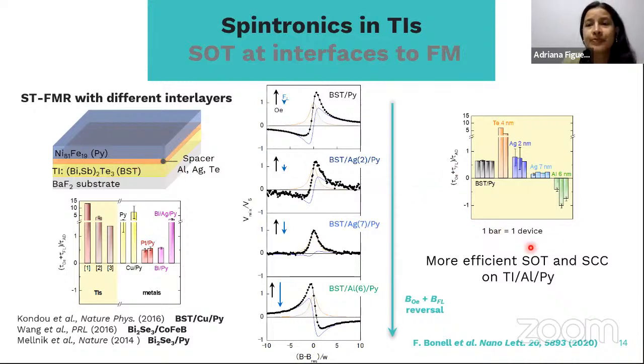So we used tellurium, silver, and aluminum, and then we saw that depending on the kind of spacer and also depending on the thickness of that spacer, we can control which contribution is more relevant, the field-like torque or the Oersted-like torque. And we observed that the most efficient spin orbit torque is obtained at the interface with aluminum. I mean, when we use an interlayer of aluminum in between the topological insulator and the permalloy.